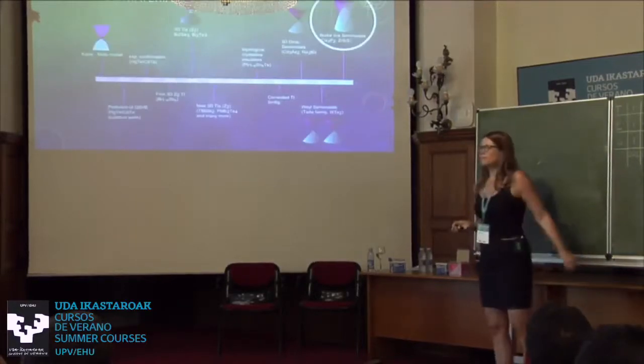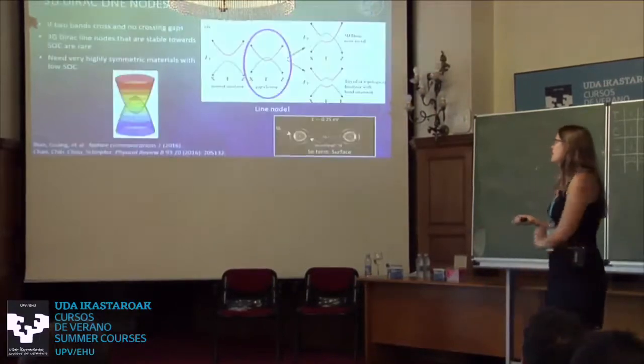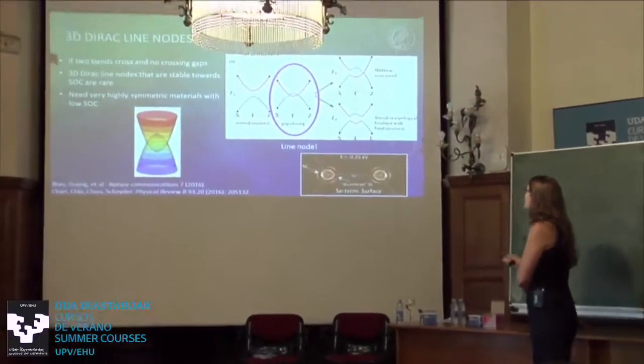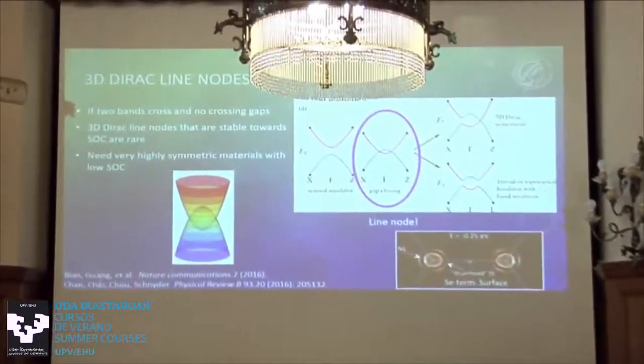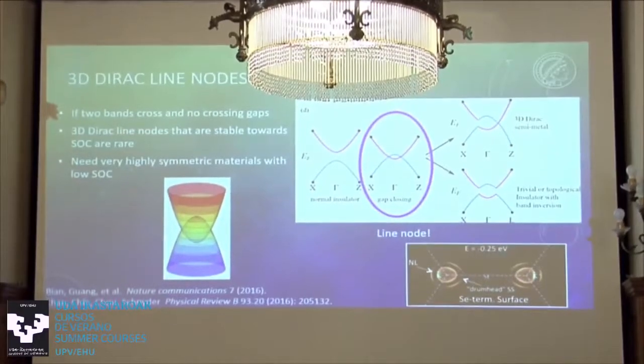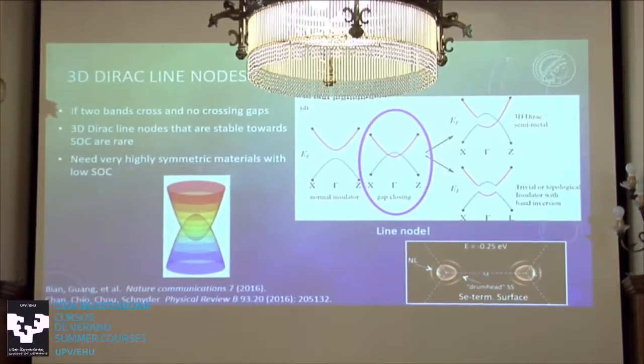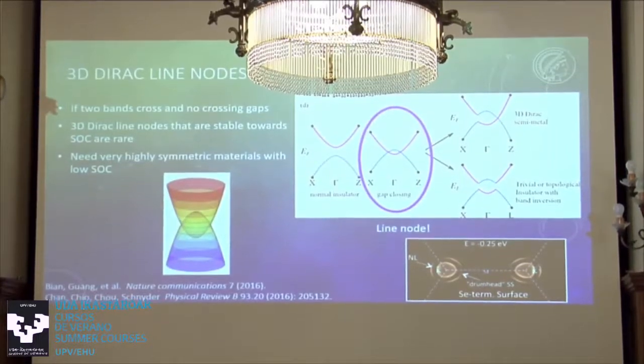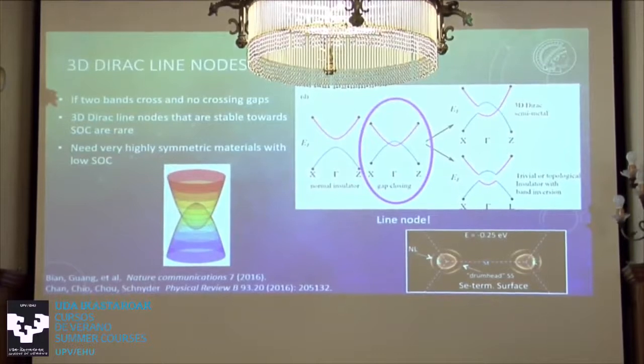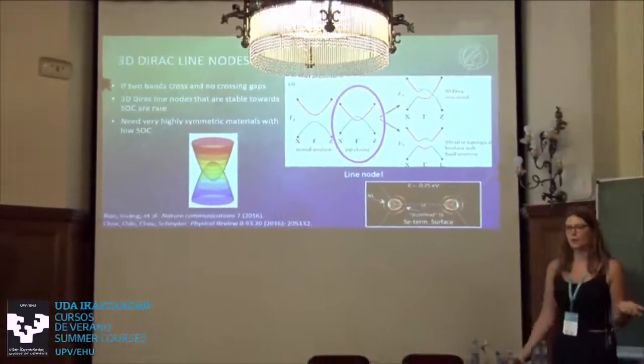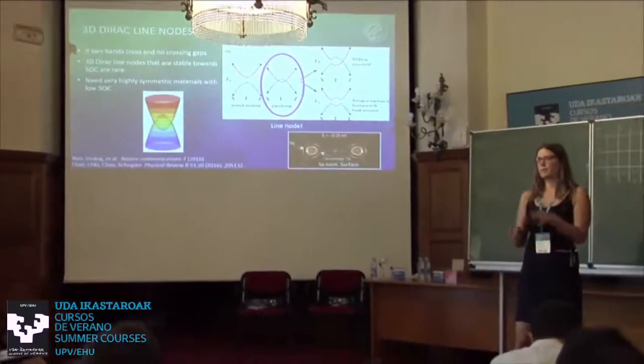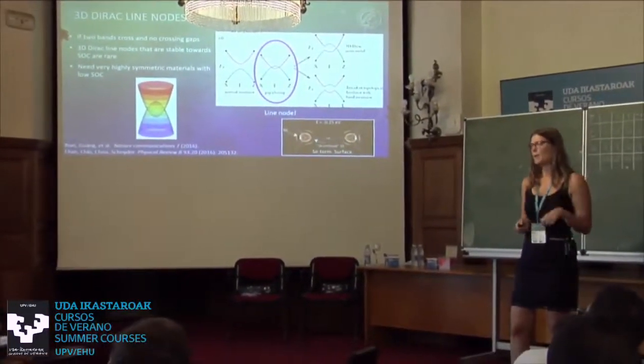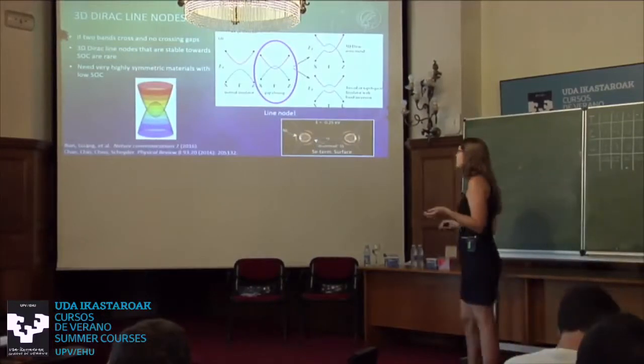Okay. Then lastly, nodal line semimetals. So this was the most recent thing on the timeline, and so what can we do to find this? If you look at this diagram again, nodal line semimetals are those where we have the band inversion and it doesn't gap everywhere. So this is really hard because we need a really, really high symmetry Brillouin zone if you want to consider spin-orbit coupling. So we need to have the nodal line somewhere along a C6 rotation axis, which is usually not possible in a crystal structure. Therefore, it makes much more sense from a chemistry perspective, if you want to look for nodal line semimetals, to look for materials with very light elements and highly symmetric. Okay? And I will also come back in my second lecture to how this can work in reality.